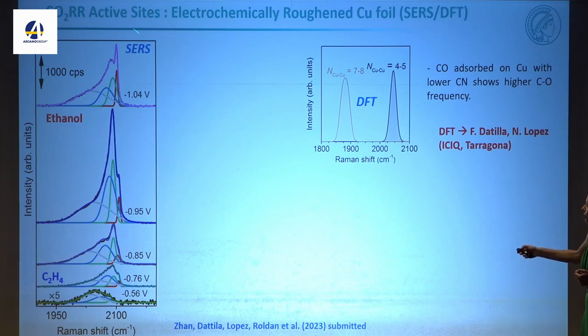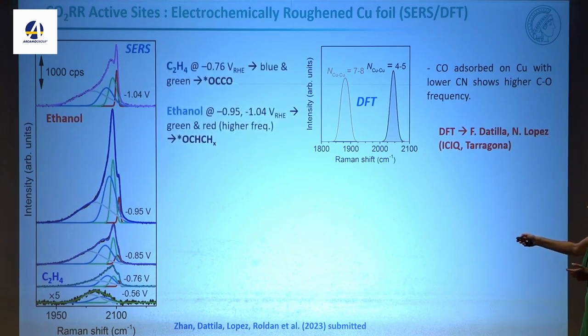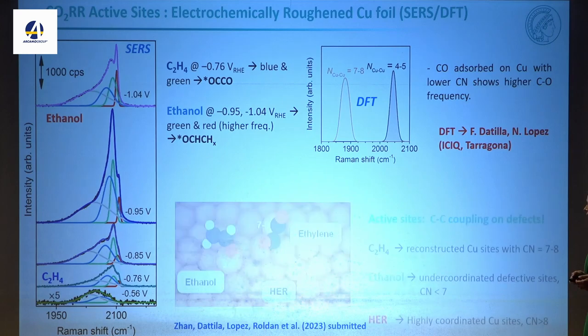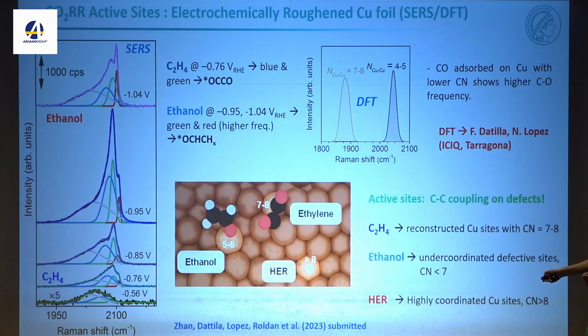So if you look at this Raman shift frequency range with SERS, here is where we are making ethanol. You can see by eye, this feature shows up here very prominently. Here's where we start making ethanol. It looks different. So you can try to deconvolute this data, working with the theorists, again, assigning different Raman frequencies to different fragments or intermediates. And we learn that if you have high coordinated atoms on the surface, same as we saw in the single crystals, then you make hydrogen. On the sites that have lower coordination, you can make ethylene or ethanol.